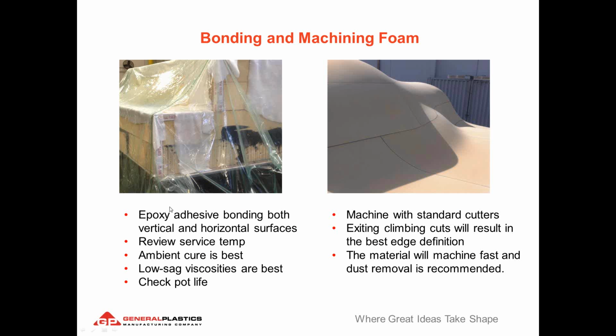So again, bonding and machining. Many different adhesives can be used, whether they're epoxies or urethanes or acrylics. But because the foam is so insulating, you want to use an ambient cure adhesive. You don't want to have to heat the foam blocks up to cure the adhesive, because that adds more time and cost by allowing your foam blocks to cool down before you can start machining them.